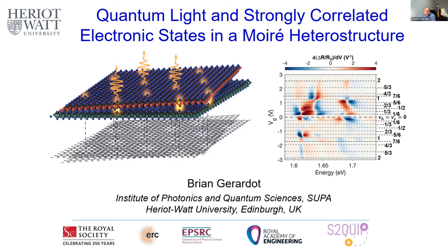And so, for instance, you can see in the schematic at the K valley, we have the ground state of the valence band spin up, whereas the K prime is spin down. And so spin-valley locking leads to some very clear signatures in the magneto-optics. And again, I won't go into details here, but basically, we can use either absorption or photoluminescence from the TMD compounds or their heterostructures to determine the origin of where the carriers reside.